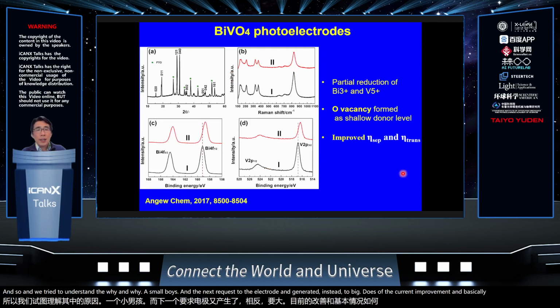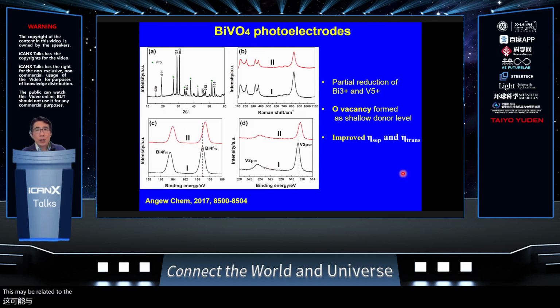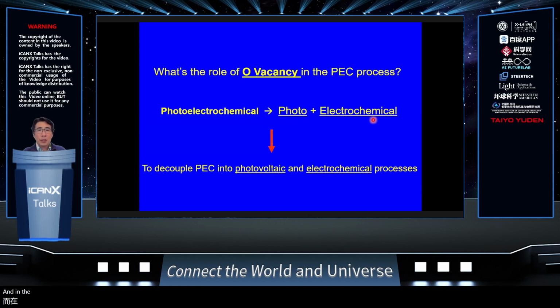This may be related to the partial reduction of species, like bismuth 3+ and vanadium 5+, which can be reduced to 2+ and 4+ respectively, and in this case generate some oxygen vacancies. The oxygen vacancies can behave like a shallow donor level, promoting charge separation and transfer, and leading to a quite significant improvement in photocurrent. From this example, we realized the importance of oxygen vacancies in the PEC system. So we tried to further continue to understand this system.